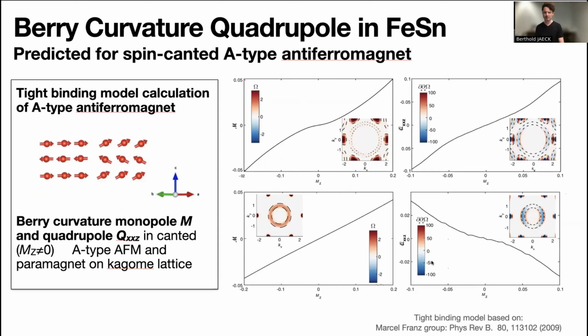You can analyze the effect of the spin canting by setting up a simple tight binding model calculation of such an A-type Kagome antiferromagnet. We've been using a very well-known tight binding model by the Marcel Franz group from some 15 years back. What we find is that if we take such an A-type antiferromagnet on the Kagome lattice and include some spin canting, we find, here in the top row, a finite Berry curvature monopole and quadrupole moment, as long as the magnetization in the out-of-plane direction, that is the canting, is finite.